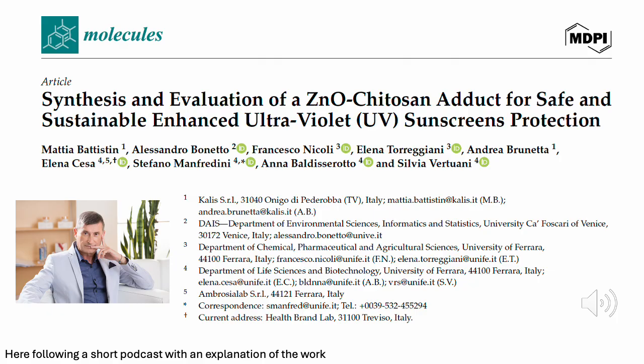But why? What's the reason for this lower toxicity? They think it might be a couple things. One possibility is that the chitosan coating acts as a barrier, reducing the amount of zinc ions that can leach out of the zinc oxide particles. Zinc ions themselves can be toxic to cells, especially in high concentrations. Okay. Another possibility is the slightly larger size of the ZnO@CS particles. Remember, we talked about that. Yeah. That might mean they're not taken up as easily by the cells. Right. They can't sneak in as easily. Exactly. So there's less internal exposure to the zinc oxide. Okay, so the chitosan is kind of like a bouncer at the door, keeping the trouble out.